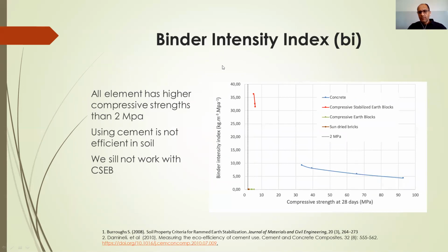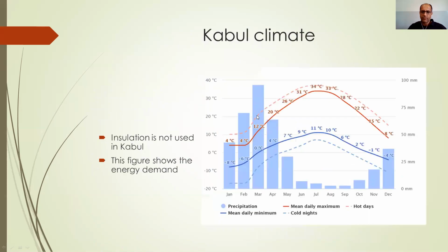We can see in this intensity index that all elements have a higher compressive strength than 2 MPa. Using cement is not efficient, because we use a lot of cement to get almost similar compressive strength. So in that case, we can see sun-dried brick and CEB have a good compressive strength. We will not use CSEB or cement, because it's not an efficient way of using cement.